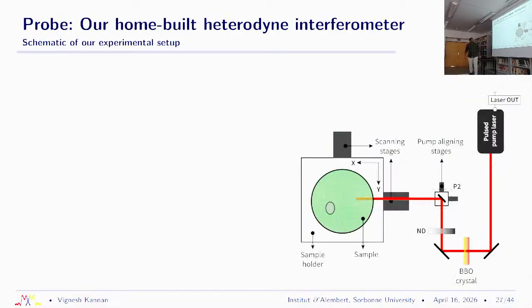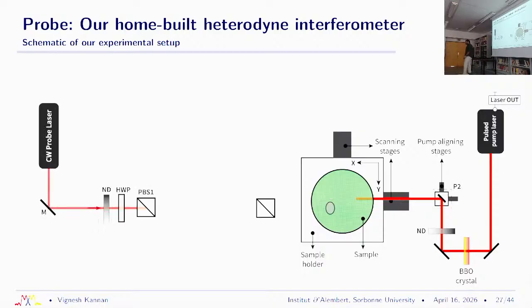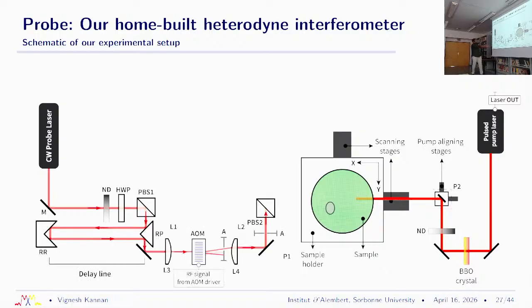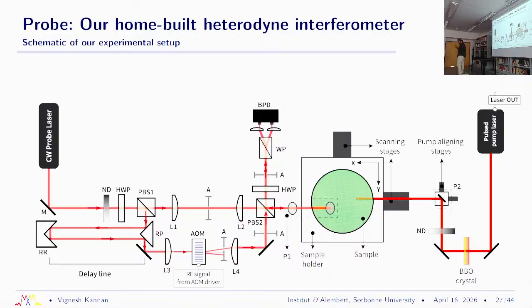So here is a schematic of the original setup. We have a sample stage, an XY stage because we needed to do automated scanning. We have a pulsed laser source that comes in, and that's exciting the wave at a given point on our sample. And on this side we have a continuous wave probe laser, which is the interferometer for measurement. We send this through a delay line, which matches the optical path lengths between your reference and your signal beam. You send this through an acousto-optic modulator, which is essentially a piezoelectric element, and this results in diffracted beams. The diffracted beam has a frequency offset of 80 megahertz from my original electromagnetic wave. And so when I recombine these two beams that come back from the sample at the photodetector, under ambient conditions I get an 80 megahertz beat. Once I have the wave that propagates, this 80 megahertz beat is distorted.